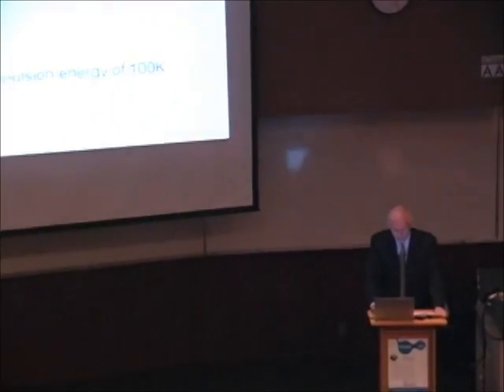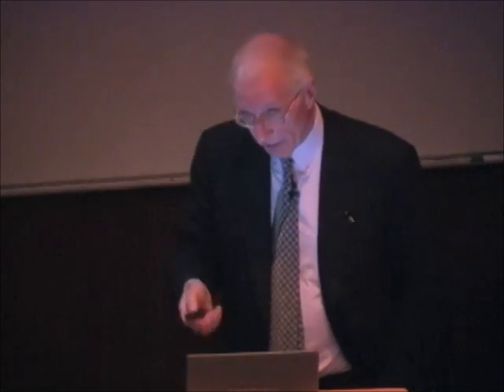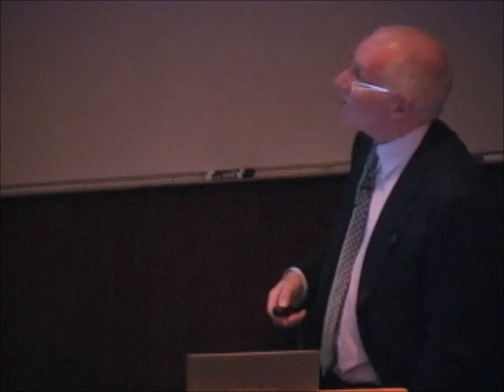Now, to give you an idea, if we just take a small sphere and ask what is the charging energy of that sphere, then for a sphere of radius 0.1 microns, e squared upon 2C, or e squared upon C, corresponds to an energy of repulsion of about 100 Kelvin. Since it goes as 1/R, we only need a very small decrease in diameter to get the charging energy to be room temperature. And this means, of course, that if we change a gate voltage on such a device, then the carrier concentration doesn't change smoothly. It basically goes in steps because the electrons are now discrete. The charge becomes discrete. Everything becomes quantized. And it's really almost a classical effect.